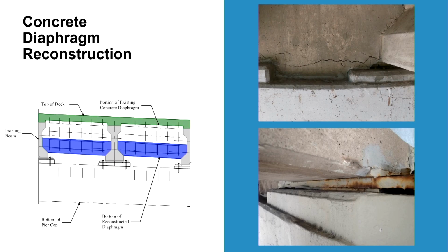As Ahmad mentioned, there's some diaphragm cracking. You can see the lateral cracks in that top photo there. When they did the joint closures in the previous rehabilitation in the 90s, they created very large, rigid diaphragms between the pre-stressed beams that are almost the full width of the pier caps and rigidly connected with anchorage into the pier caps.